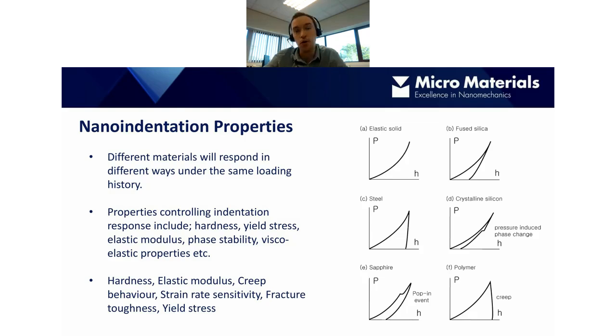And then on the other end of the scale, we have maybe some polymers or soft metals in particular. We can have almost entirely plastic deformation, where the unloading curve almost comes down vertically because there's very little elastic recovery. Normally we'd have a hold period at maximum load, so we get a step at the top of these indentation curves, especially for polymers.